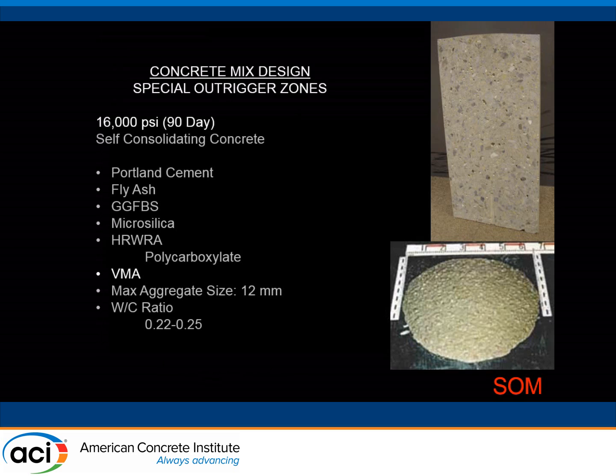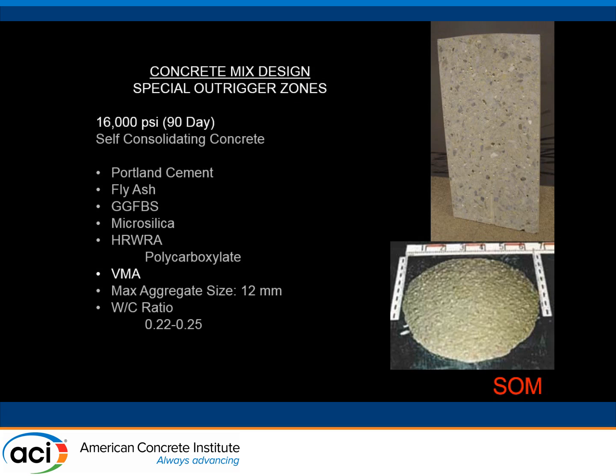The reinforcement ratios were fairly high, which was certainly the reason why we wanted to go with self-consolidating concrete along with the high strength. So some details about the mix design for the special outrigger zones. 16,000 psi was specified at 90 days. Self-consolidating concrete, and you see the main ingredients of the mix: Portland cement with fly ash and slag cement replacement. Microsilica was also used, and then we have a high-range water-reducing admixture coupled with a viscosity-modifying admixture to stabilize the mix for the self-consolidating concrete.